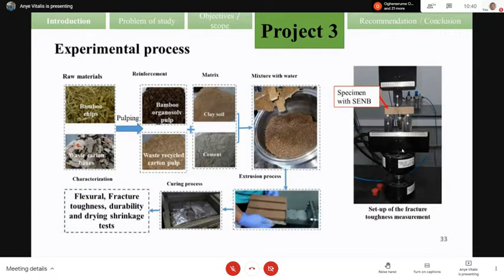So in this project, we use the same formulation that has been done for project 2, but the difference is that now the composite has been machined to a dimension of 80 by 20 by 15, and now all the surface has been polished to see how the crack is moving. And we apply a 3-point bending test for flexural strength, and also a 3-point bending test with displacement with single edge notch beam to study the fracture toughness of our material under MTS equipment.